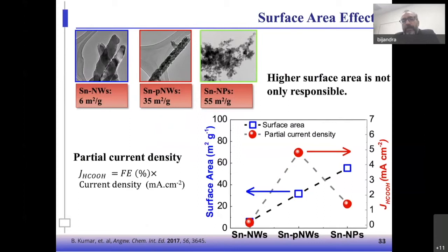So one question can come: because this porous nanowire has higher surface area in comparison to nanowire, the higher catalytic activity may just be coming from the higher surface area. So we tried to compare the experiment with a tin nanoparticle. Here we can see that in the case of tin nanowire, the surface area is 6 meters squared per gram, and for porous, it's 35 meters squared per gram. While for nanoparticle, it's 55 meters squared per gram. So if it were the surface area, this nanoparticle must have higher catalytic activity. But our results show that the porous nanowire has higher current density for formic acid production, even in comparison to this nanoparticle. So what does it mean? It means the higher CO2 electrochemical reduction performance is not attributed to surface area alone. It's attributed to the intrinsic catalytic property of this porous nanowire.